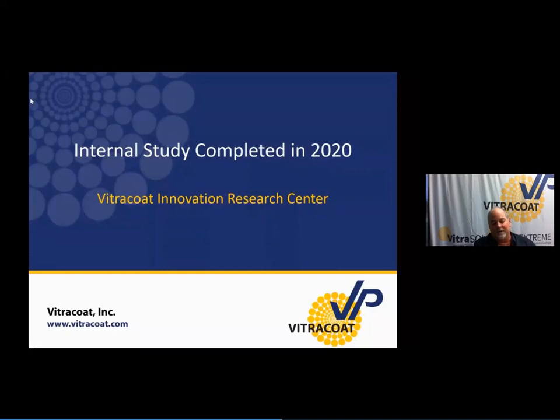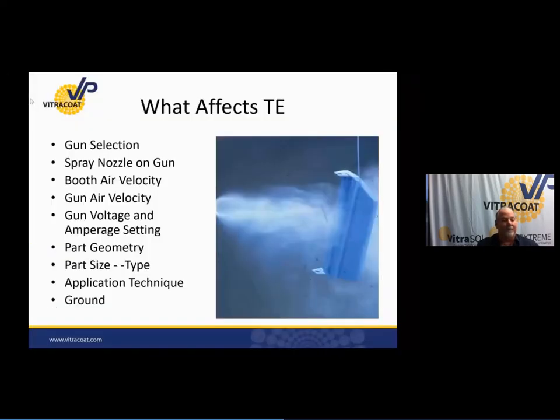Our Vitracoat Innovation Center in 2020 did a study on transfer efficiency. We looked at all the variables, or the most important variables, that can impact transfer efficiency. And this is what we found. We found that gun selection absolutely can impact transfer efficiency. The nozzle that you use on the gun can impact transfer efficiency. The booth air velocity will impact transfer efficiency. The volume of powder or the velocity of the powder coming out of the gun will impact transfer efficiency. The voltage and amperage setting on that gun, of course, will impact transfer efficiency.